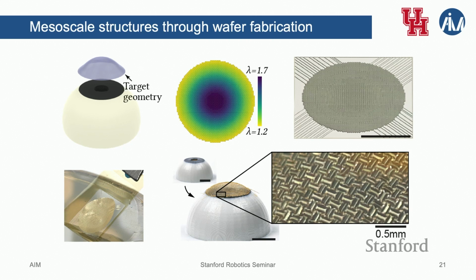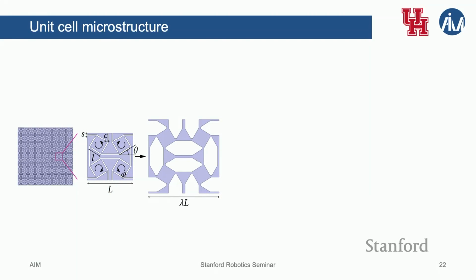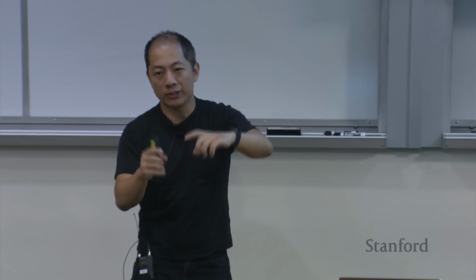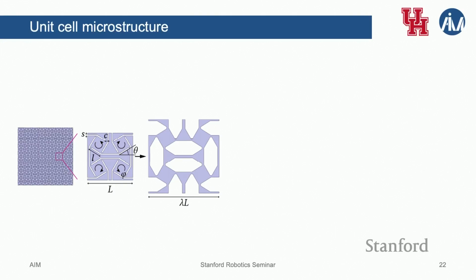We're going to go through each bit of this so that you have an intuition of how this works. The unit cell looks like this. It's a very simple architecture. There are 4 squares formed by us cutting these lines out. And if we rotate these squares by a fixed angle, we get this shape. And this transformation is bistable, because you can imagine initially this square is in this shape. When it's rotated by half this amount, the length of the square effectively increased, right? Because it went from the orthogonal to the diagonal, so something is getting compressed. And then when it goes all the way over, the compression eases and you go into a local energy minimum again. So that's the mechanism.